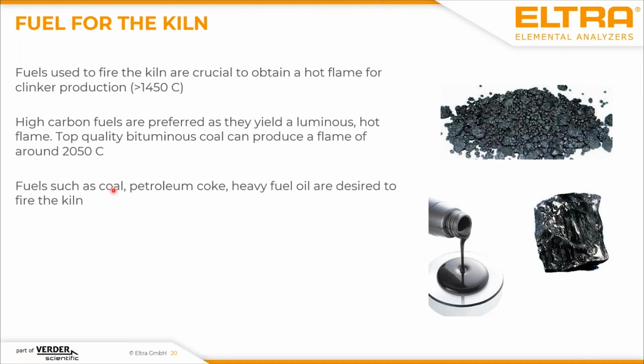The fuel for the kiln is usually some organic fuel like coal or coke or heavy oil, and the higher the carbon content is, the more energy we get, the more heat we can get. For the production of clinker, we need a temperature higher than 1450 degrees, and to reach that, the fuel must be very well selected and controlled in order to receive those high temperatures.